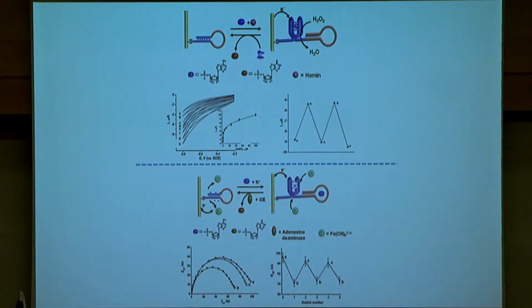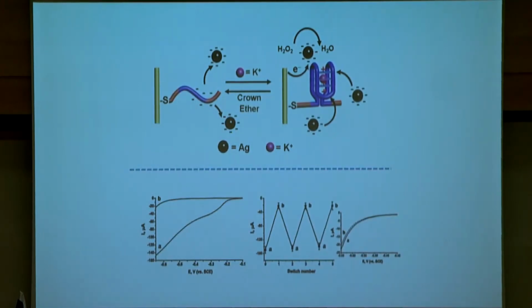We can use this control of the interfacial electron transfer properties also to catalyze different catalytic transformations. For example, silver clusters or silver nanoparticles are negatively charged because of the capping of the silver cluster. When we have a normal, negatively charged nucleic acid, then these catalytic nanoparticles are repelled from the surface. But when we generate the G quadruplex, we allow electrical contact between the nanoparticles and the electrode that will effectively catalyze the reduction, for example, in this case of hydrogen peroxide. And again, in the presence of crown ether, we can switch on and off the catalytic functions of the electrode.